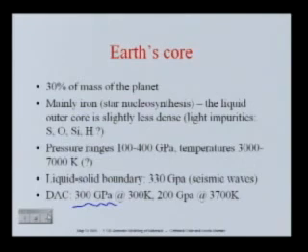And so we'll see here how ab initio simulation, and in particular thermodynamic integration, has been used to figure out what is going on in this region here. And as usual, you need to make sure that you believe your energy models. So these are a couple of validation curves. This is for HCP iron, one of the high pressure phases, and a comparison between experimental results and simulation, where the simulations are the solid lines, and you see it agrees very well in describing the equation of state, pressure versus volume in this case.